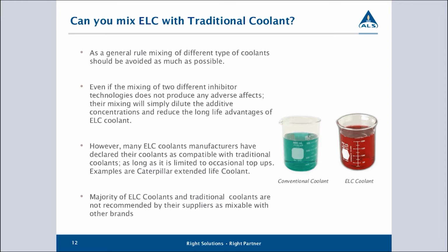Can we mix a coolant? And the simple answer to this is no. We really shouldn't mix two different coolants together unless we properly understand what it is that we're dealing with and what the chemistries are that we are working with. So as a general rule, I strongly recommend that we do not mix coolant unless it is an emergency situation. We have no choice but to keep a system running, you have to put in a different coolant. When that occurs, I recommend that at the earliest opportunity, we drain what is in the cooling system and refill with whatever is the main coolant that you would typically use in the system, just to get that mixture